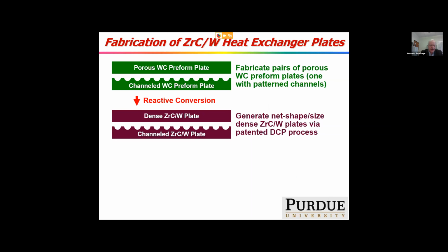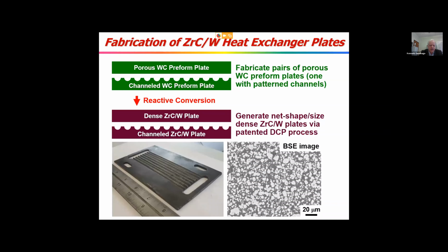So then we take plates like that and we undergo the DCP process with a melt infiltration. There's an example of one such plate. Again, it retained its shape and dimensions to within 1%, and the microstructure on the right shows that it's fully dense. Again, gray ZrC-tungsten-based matrix and brighter tungsten-bearing particles.